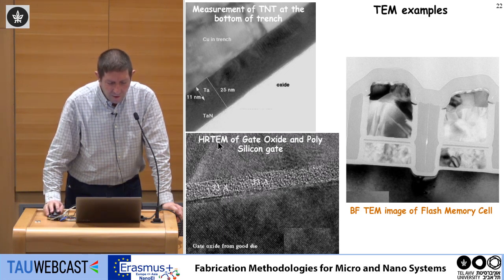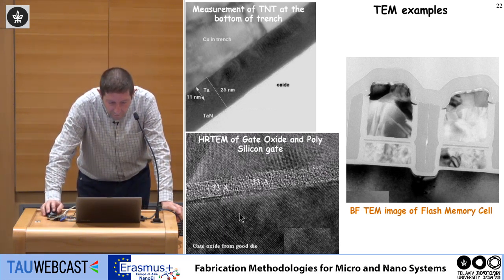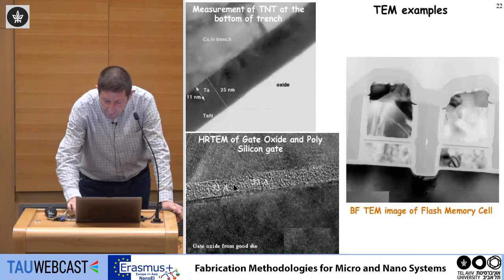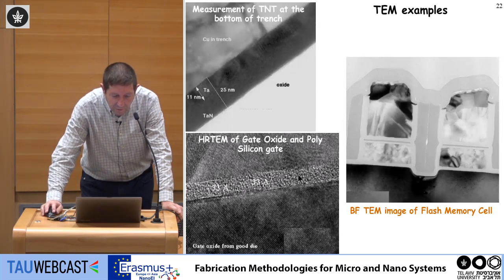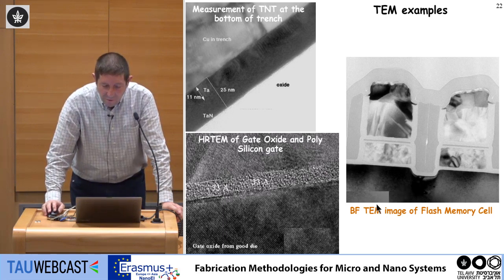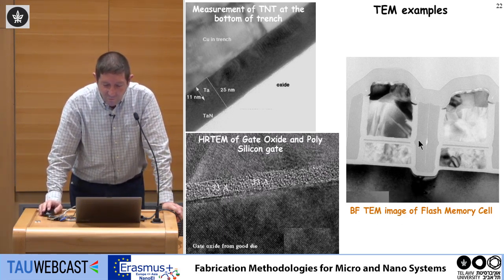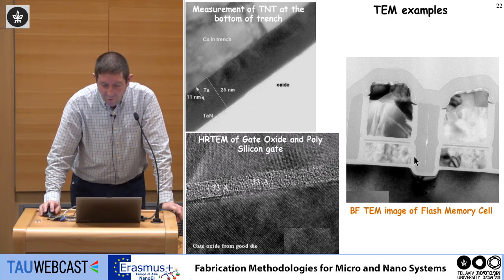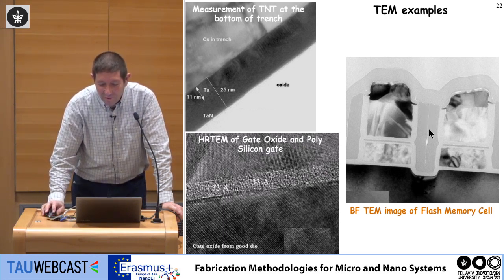What do we have here? This is high resolution TEM of gate oxide and poly. So this is the silicon, this is the polysilicon, and this is the gate oxide. And you can see this is amorphous material. And you can see here, this is atomic resolution imaging. And this is a bright field TEM image of a flash memory cell. I have to guess what it is. But what you see here is the trench, the contact. And you see, by the way, it's very nice here. Whoever did this technology had some problems in filling. If you look very carefully, do you see the seam here in the center of the via?